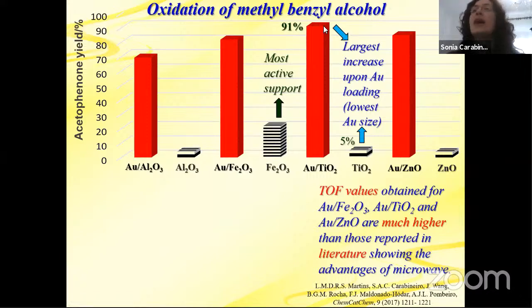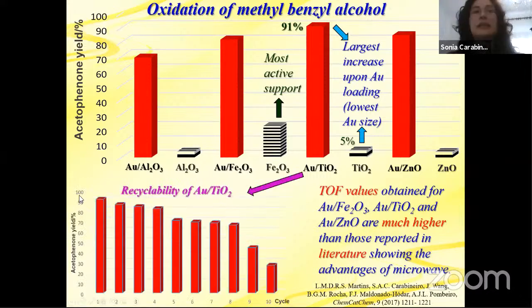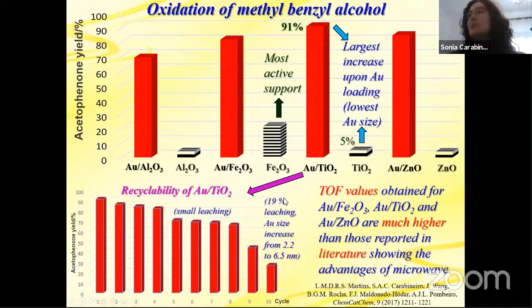So we did some recycling tests of gold on titanium dioxide, and we see here up to 10 cycles, and we see here that up to here is fine. Here at the 5th cycle, we start to have a small leaching, and then here at the 10th cycle, we have already 19% leaching, and the gold size from 2.2 to 6.5 nanometers. So that is the problem.